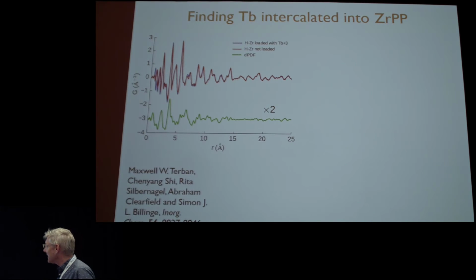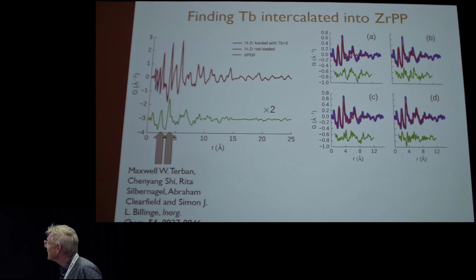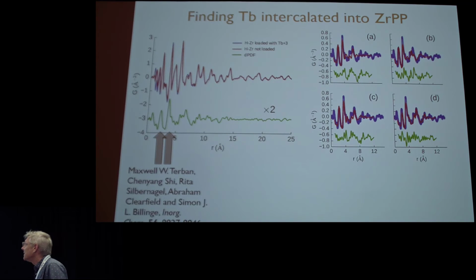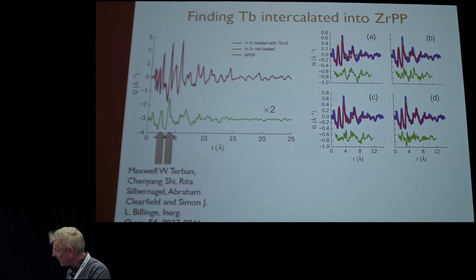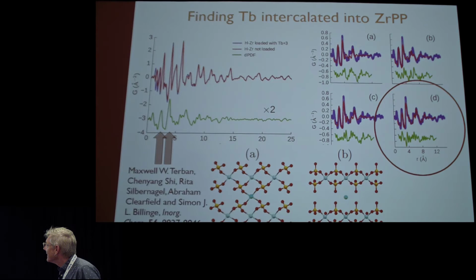And so what we can do is we can do simple things. Again, this PDF is such an intuitive function. We can say, well, there's a high probability of finding an atom at this place, like 2.5 angstroms away from the terbium, so that's terbium to oxygen probably. And then this one here is the terbium to phosphorus. We can infer that. But actually we have this full signal, and what Max was able to do was again to take competing structural models that he took from databases of terbium phenolic, terbium phosphorus compounds, and he found different candidates. And he finds an amazingly good agreement with one of these that goes all the way out to 12. So that basically tells us in a high amount of detail exactly what the local environment of this terbium is. It's highly specific. And it's actually looking like this, so we can extract what it looks like in the material.